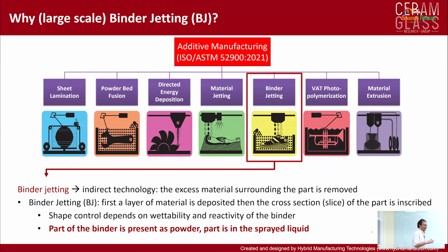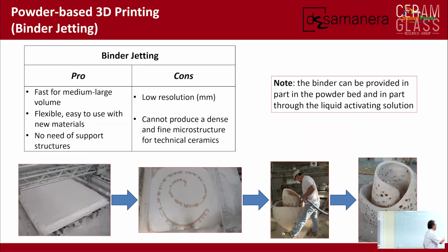The advantage of this approach is that, again, we can use corrosive materials. On the other hand, being a large-scale printer, the resolution is low. So we use this printer for making components for applications that are different from the ones that I mentioned before. The advantage of large-scale binder jetting is that it is fast for medium-large volumes. The printer has a printer bed of 2 meters by 2 meters, and you can print up to 2 meters. You might say that this is not large scale, but after printing, you need to move the part and transport it, and 2 meters wide is the maximum allowed on a truck in Italy, so there is a reason behind that.